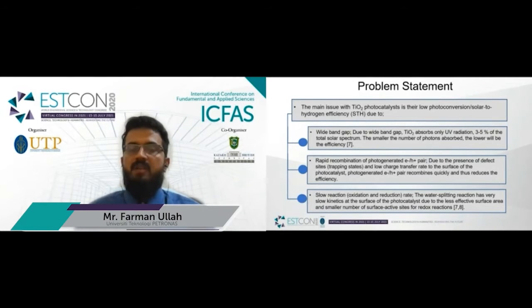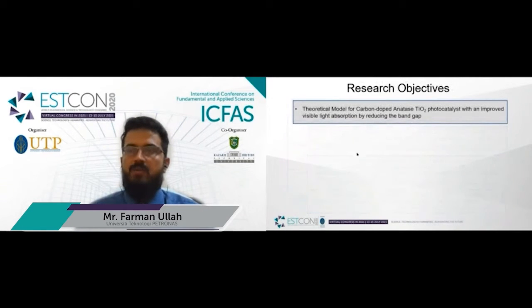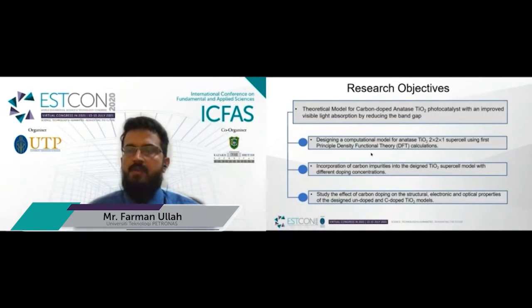So, for the current research work, the objective is to design a theoretical model of carbon-doped anatase TiO2 photocatalyst with improved visible light absorption by reducing the wide band gap energy. For this purpose, we have designed a computational model of an anatase TiO2 2x2x1 supercell using first principle DFT calculation. Then we incorporate carbon impurities into the designed TiO2 supercell model with different doping concentrations, and study the effect of carbon doping on the structural, electronic and optical properties of the designed undoped and carbon-doped TiO2 models.